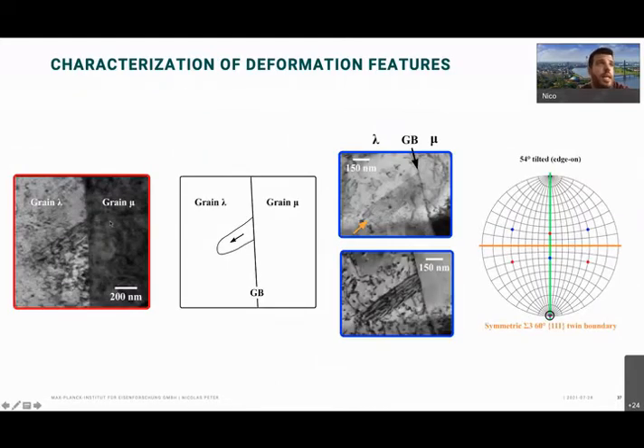Some might have already the guess that these are stacking faults. So we have some during in situ deformation where we can observe they come out of the grain boundary. So it seems we have stacking fault nucleation from the grain boundary into the grains. This is the contrast given here, the stripe contrast. And here we even see the leading partial coming out. We also confirmed this by stereographic projection here, that we have the nice mirror symmetry of the reflections.